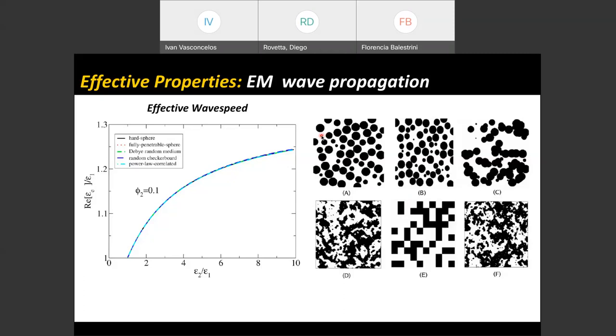Now, what you see here on the graph is the real part of the effective dielectric constant. So this is telling us about wave speed, scaled by the white part. On the horizontal axis, you see this calculated as a function of contrast. So the white part is kept fixed, and then we change the contrast relative to the black part. The volume fraction is also fixed at 10%. Notice that all of the curves overlap.